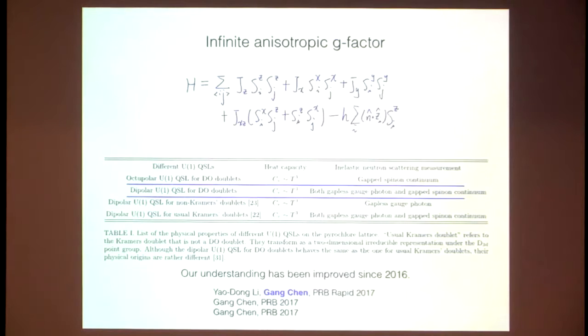One idea is to apply a magnetic field to the system. The x and y components are so-called magnetic multipole degrees of freedom, so they do not linearly couple to the external magnetic field. Only the dipolar component, which is the Sz component, couples to the magnetic field. So the magnetic field naturally selects the Sz component.